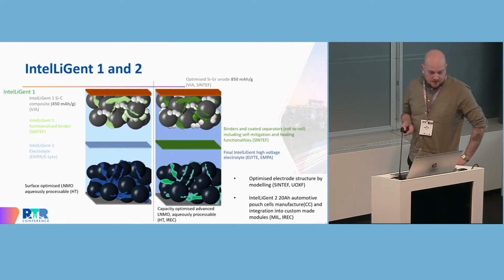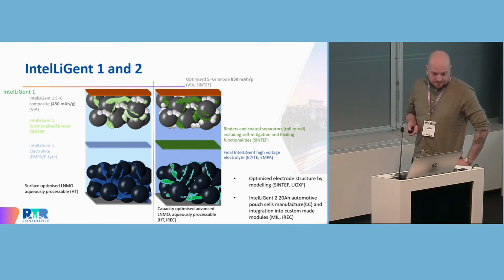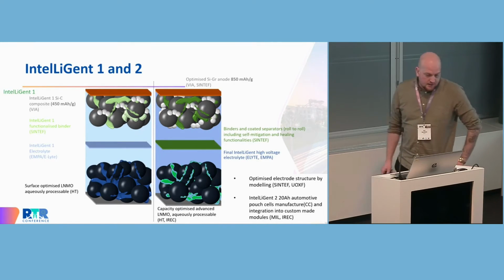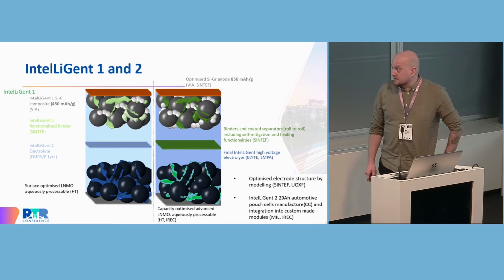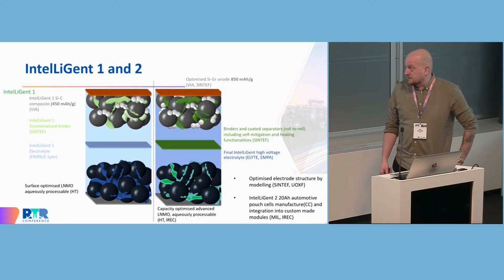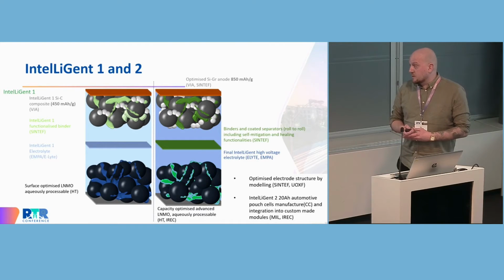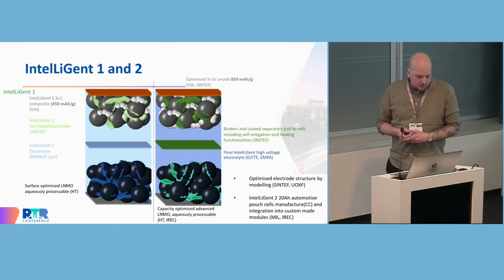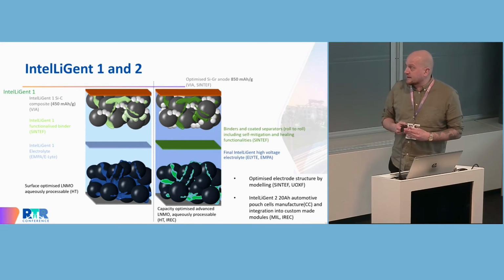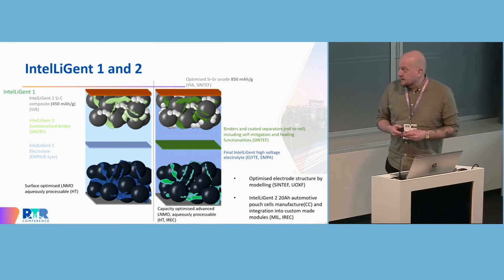So we intend to build the Intelligent batteries in 2 iterations or generations, where we have an interim scale-up that is to happen now in the next quarter. That will then consist of a silicon graphite anode delivering 450 milliampere hours per gram, paired with a surface-optimized LNMO cathode, which is aqueously processable. First generation of a high voltage electrolyte, as well as functionalized binders.